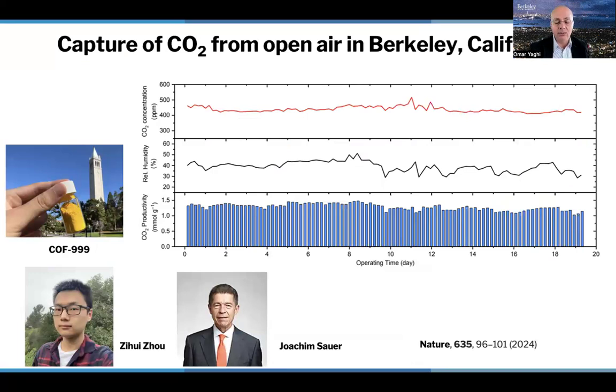And we didn't waste any time in testing the material and its performance in using Berkeley outdoor air. So we just piped in the air from the atmosphere of Berkeley into the material. And this is the CO2 uptake. You see the CO2 uptake here at the bottom over 20 days. And it goes up and down because it's influenced by the amount of water in the air.